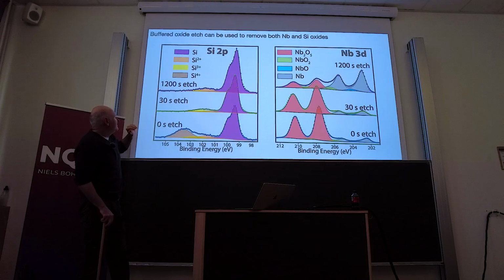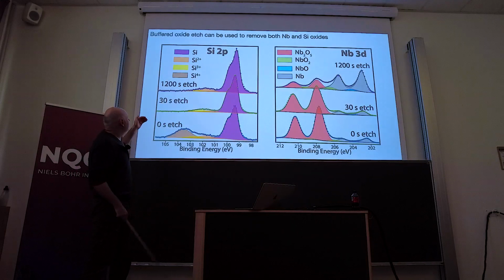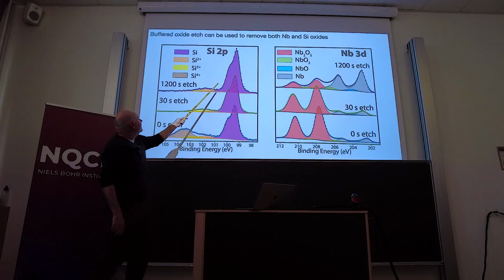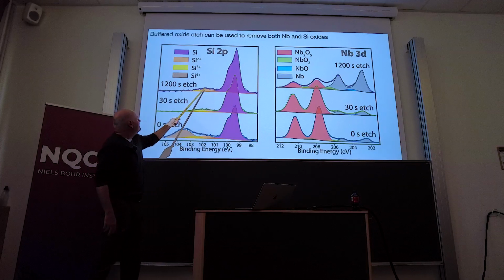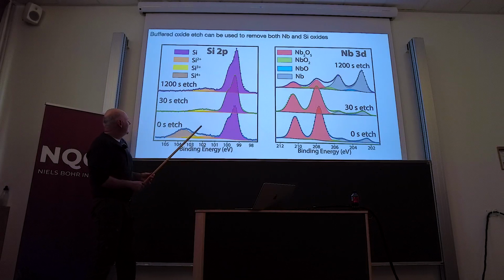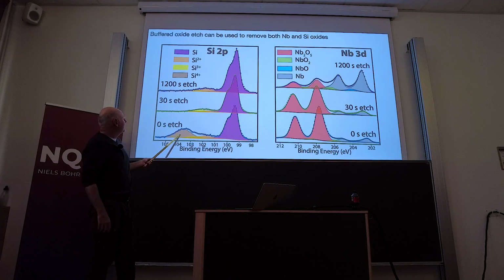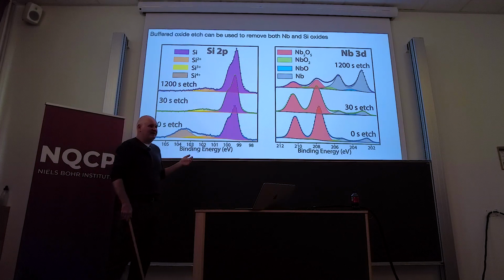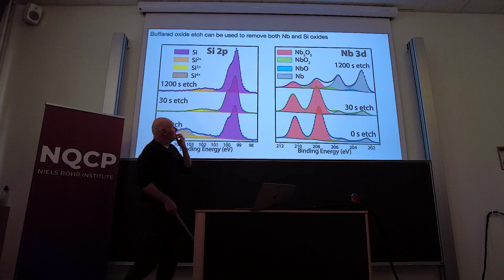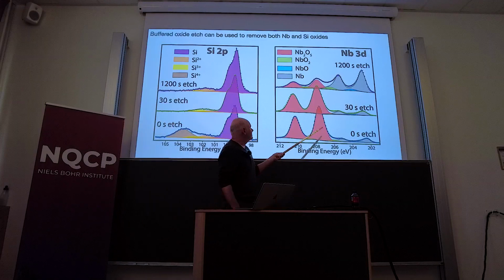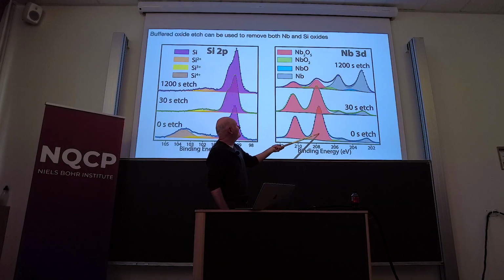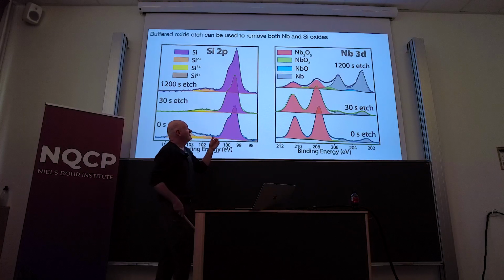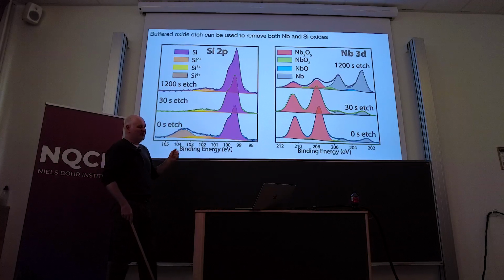And so you can see that essentially what we have here on the top is essentially pure silicon with a tiny bit of silicon 2+. And at 0 time, we have silicon 4+, which is basically silica, amorphous silica. Same with the niobium. At 0 time, we're dominated by Nb2O5. And after 1200 seconds, you at least reduce that and have more niobium character.